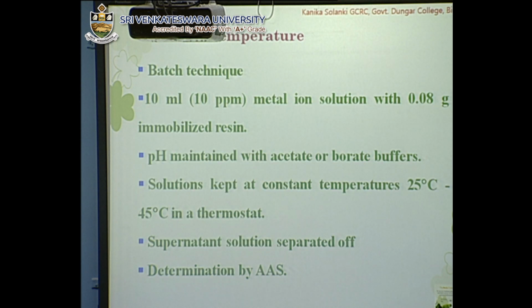Effect of temperature. To investigate the effect of temperature, we have used the batch technique. The solutions were kept at constant temperature between 25 degrees centigrade to 45 degrees centigrade in a thermostat. The supernatant solution was separated off and determined by means of AAS. The absorption increases up to 35 degrees centigrade, it becomes constant up to 45 degrees centigrade, and then it decreases marginally. The effect of flow rate was also investigated by the column method. The most suitable flow rate found is 2 ml per minute.